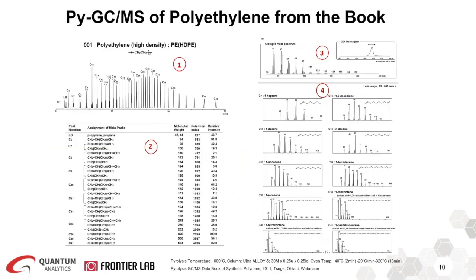So here is an example page from the book for Pyrolysis-GC-MS of polyethylene. As you can see here, the pyrogram of the polymer, in this case polyethylene, that was performed at 600°C is shown as number 1. Number 2 category is the peak assignment table together with the molecular weight, relative peak intensity, and the retention index. Number 3 is the EGA thermogram that was performed from 100 to 700°C at a rate of 20 degrees per minute, as well as the average mass spectrum of the EGA. And number 4 category is the mass spectrum of the top 10 major peaks. So F-Search is the search engine software that contains all that information from the book.